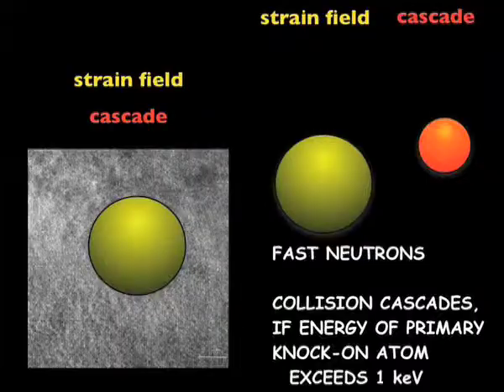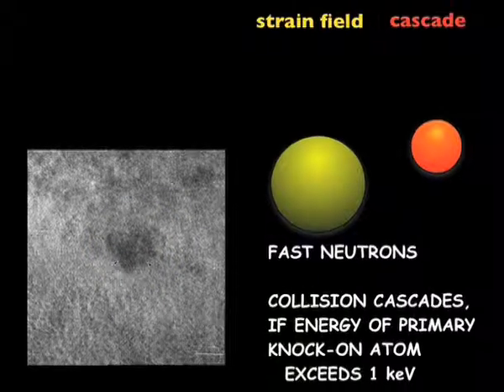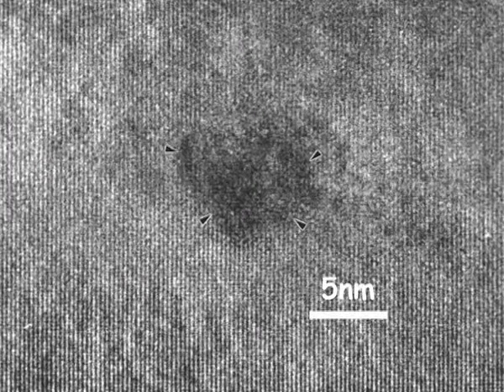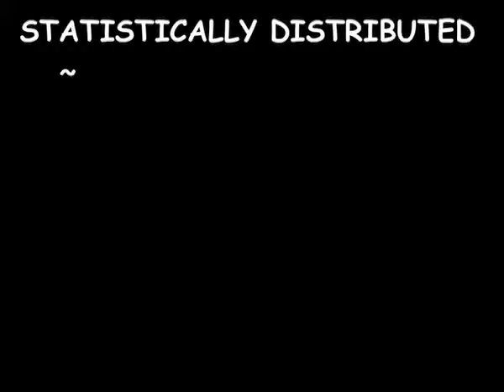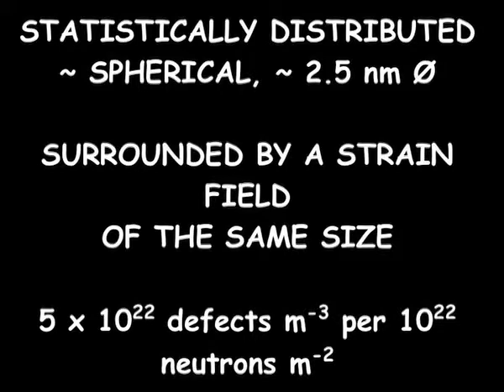Whatever particle or source you use, you have to first of all check very carefully which kind of defects you are producing. The fast neutrons transfer so much energy locally to the materials that parts of the material locally melt and recrystallize, or remain amorphous, and produce spherical, statistically distributed defects in the material with a size of about five nanometers.